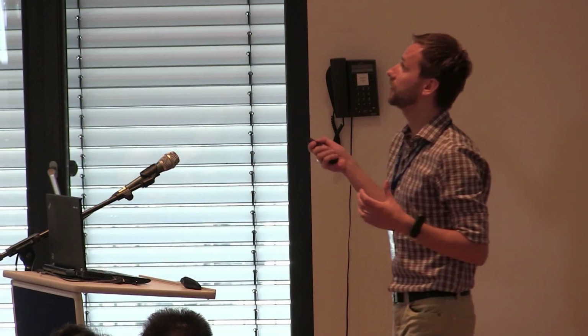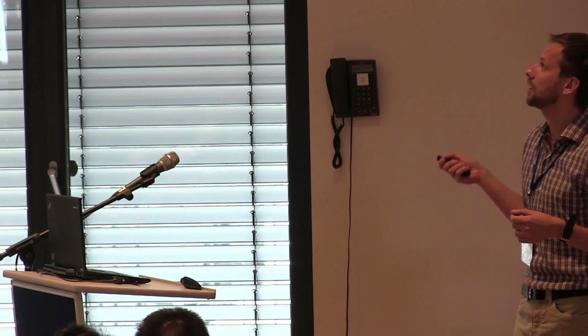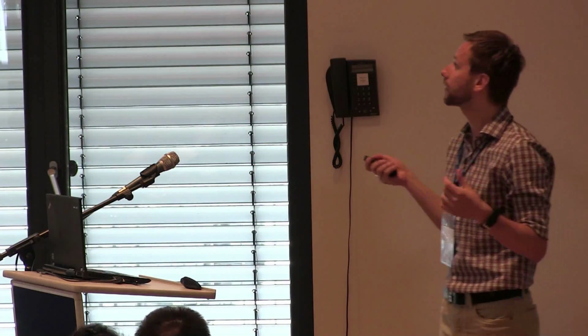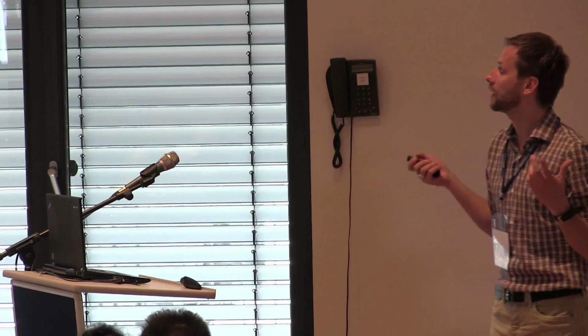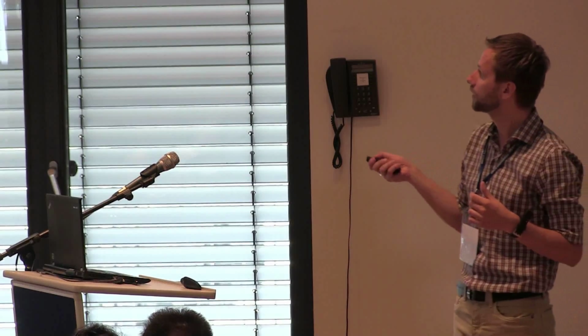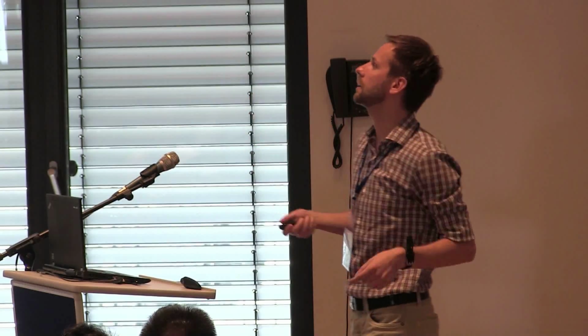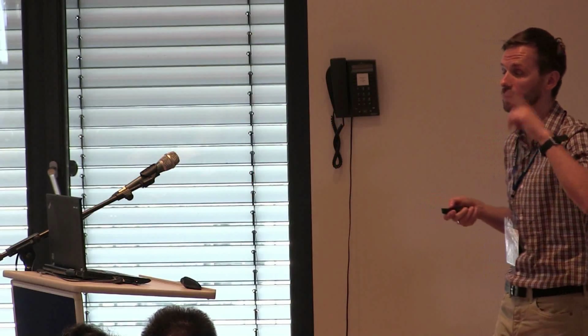When we want to understand the physical picture of this limitation of the high speeds for graphene transistors, we need to acknowledge the fact that the graphene MOSFET, the high-speed MOSFET, is a strong-field device. If you have a gate length on the order of 100 nanometers and a source-to-drain voltage of about 1 volt, and you can't go much lower because you need to be much higher than kT, then the field in the channel will be on the order of 100 kilovolts per centimeter. And then you want to modulate the currents by this strong field at the terahertz rate.